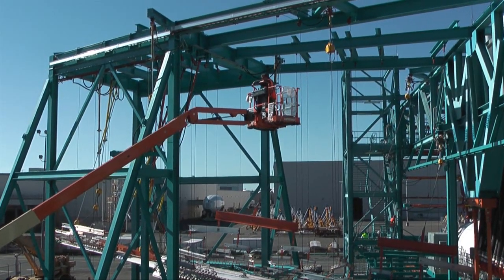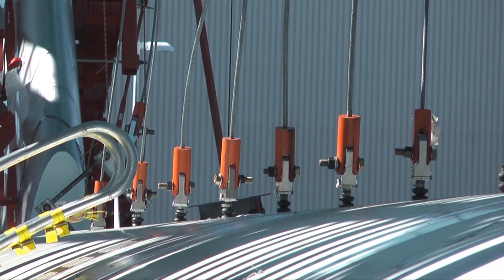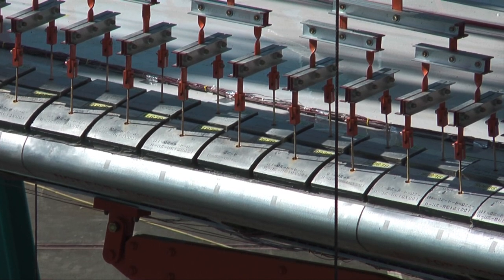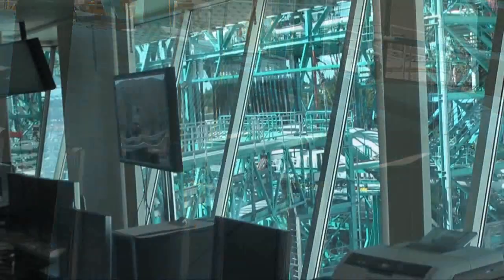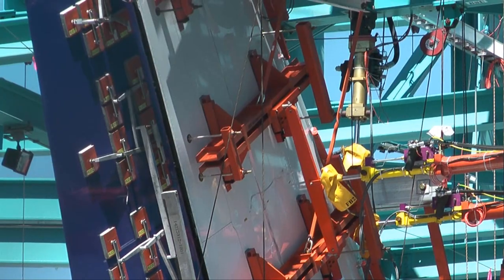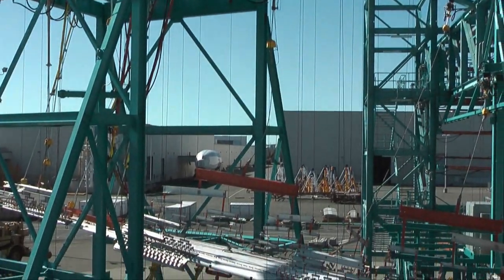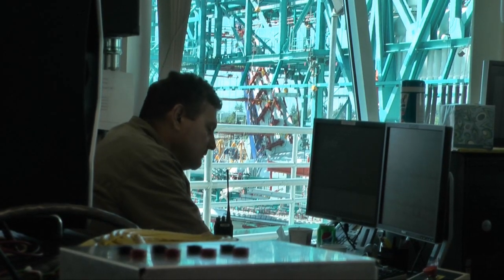To simulate multiple flights, Boeing mounted the airframe onto a specially designed test rig and then connected more than 100 mechanical devices to the exterior, from the leading edge of the wing to the tail fin to the fuselage. With this setup, engineers in a nearby control room can direct the devices to apply loads to the plane, basically pushing and pulling on the surface over and over again, so it mimics the ground-air-ground cycle — going from taxi conditions to take-off, cruise, landing, and again taxiing to the terminal.